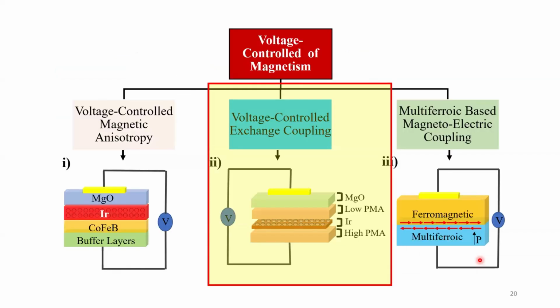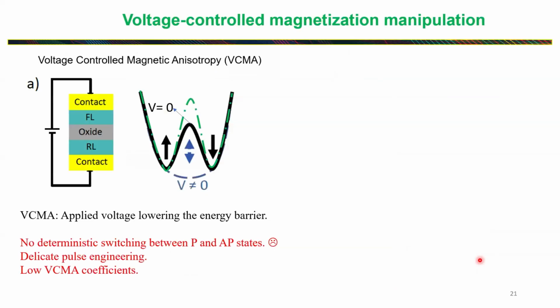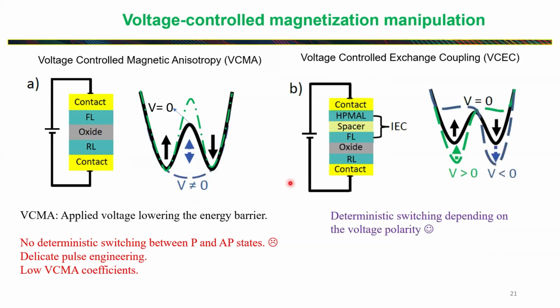Okay, the second one is voltage-controlled interlayer exchange coupling. As we said in the VCMA part, when you apply voltage, for one polarity you increase the PMA, and for the other you decrease the PMA. But this is not deterministic in nature, and hence it creates a problem. So we recently came up with a new way of doing this voltage-controlled switching, which is called voltage-controlled exchange coupling. You know that there is RKKY coupling between two ferromagnetic metals when you put a non-magnetic metallic